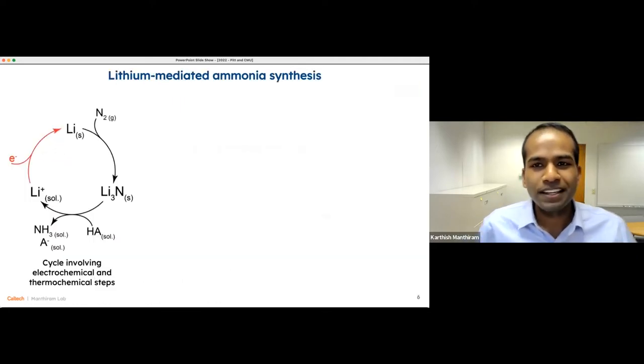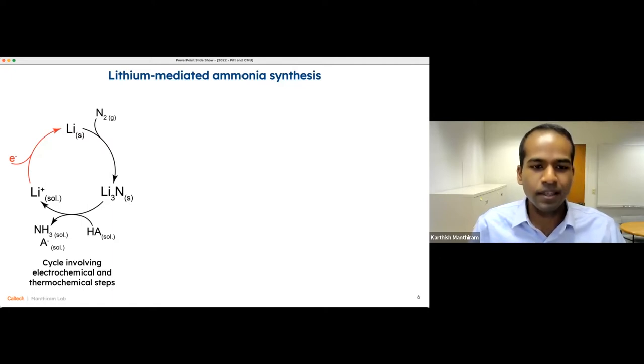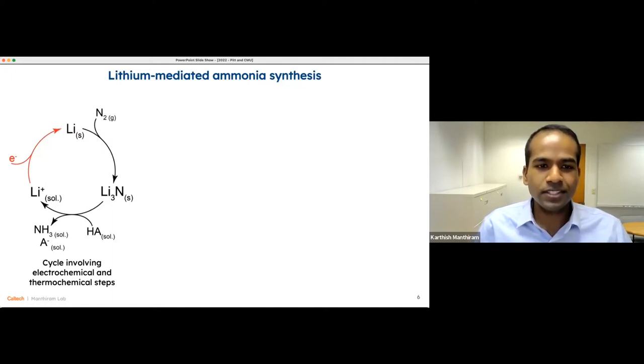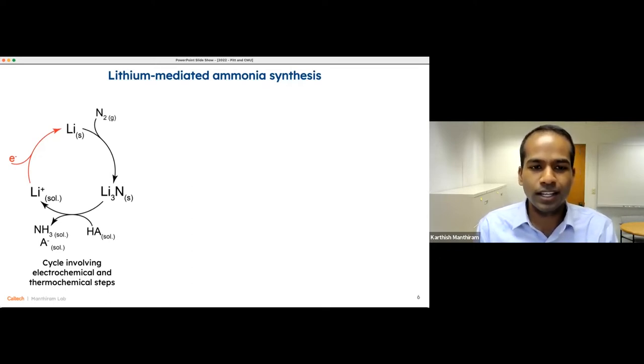So the previous slide may give you the impression that this should already be possible electrochemically, and that this is the way the world should be conducting this reaction today. But it turns out that catalysts for doing this reaction are really underdeveloped. And so here we are using lithium metal as a catalyst to drive nitrogen dissociation. So we're leaning on lithium to do what is probably the most difficult step of this reaction, breaking this inert and strong nitrogen triple bond.